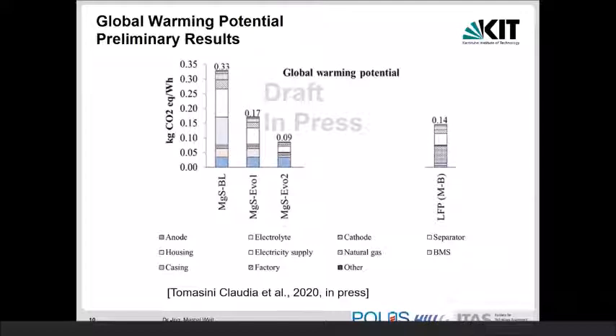But I have to say, this LFP data set is already quite old. That means it's from 2011. Present LFP systems, maybe even the new one from BYD or Tesla, could be significantly lower. So that would be quite interesting. But at least you see, if you improve the cell in a certain way and make it more comparable to a lithium-ion battery cell, then you are in a certain way competitive, and that's already quite good. Now let's see in detail where the differences in the impact come from.